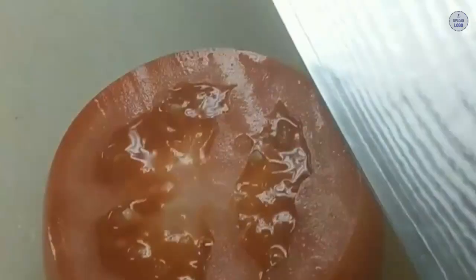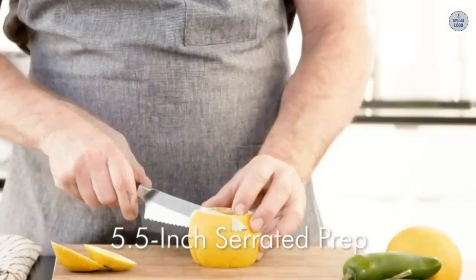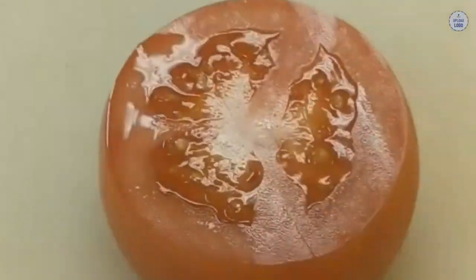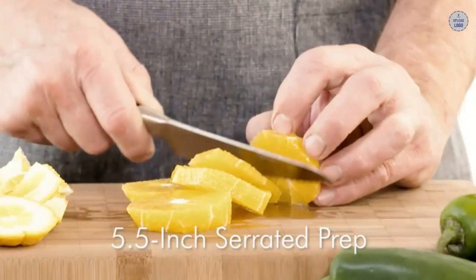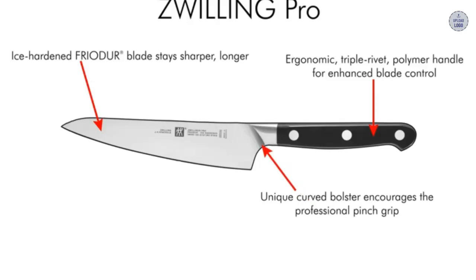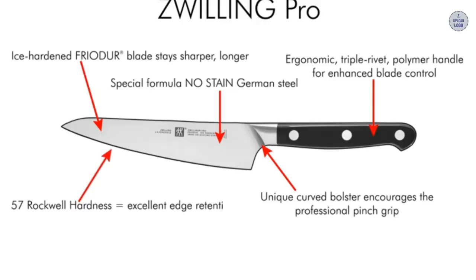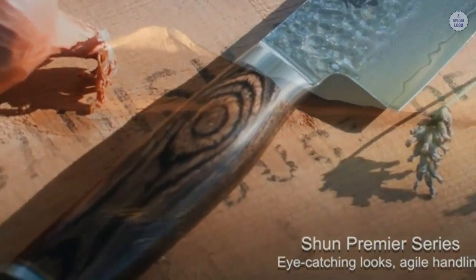The big benefit of not having a very high carbon content is that higher carbon steels are usually more brittle, therefore the 0.55% content keeps the blade durable. That's the same with the vanadium of 0.4%. Vanadium improves the resistance to wear of the steel, also adding to its durability. The chromium content is 15%, which is what the 15 in X50CrMoV15 represents. Chromium is vital for the durability of steel as it's what makes stainless steel resistant to rust. Steel need only be 10.5% to be considered stainless, so a 15% content is high and makes this a quality stainless steel, very unlikely to rust unless extremely mistreated by the owner.